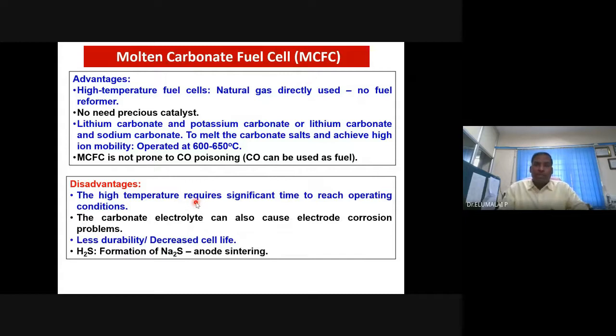So we have several merits for this fuel cell, MCFC. Not only carbon monoxide, natural gas directly can be used as a fuel. You don't need to reform into hydrogen. CNG can be directly used. Methane can be directly used because of high temperature. Anything can be oxidized at an elevated temperature. You don't need a precious catalyst because the rate at which the oxidation takes place is supported by the high temperature of the fuel cell operating condition. And you don't need to have a precious catalyst, platinum.